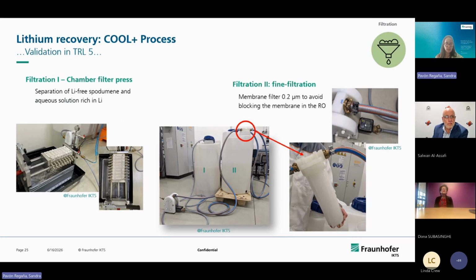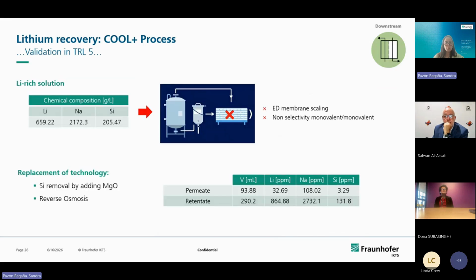Once this is done, we have to cool down overnight, obviously. And then we proceed with the filtration. We have a 2-step filtration. First, we have a chamber filter press in order to separate the residue. And then we have a fine filtration in order to avoid blocking of the membrane in the reverse osmosis. Once we have done this, we could proceed with the electrodialysis, but we have some challenges. We have silicon there, and then we got some problems in our membrane, and we needed to switch technology. That is why we replaced this electrodialysis technology with reverse osmosis.